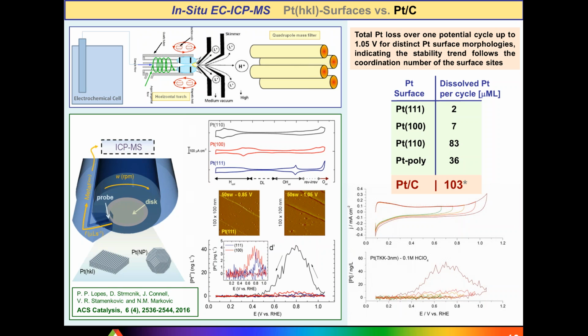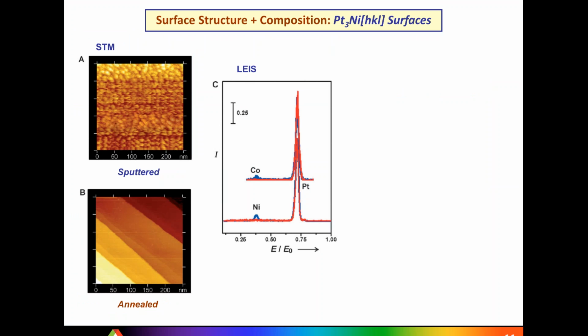So now I will switch gears into something which is related to what we can do, and the first question is what we can do to improve activity. So, alloying is something which is well known. Those are results that are coming also from our group. I would say that was early 2000s. I was looking into platinum cobalt and platinum nickel alloys in vacuum first. So extended, well-defined surfaces. Later we switched to single crystalline surfaces.